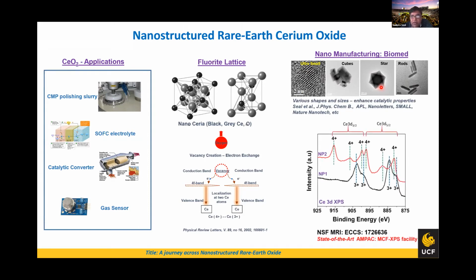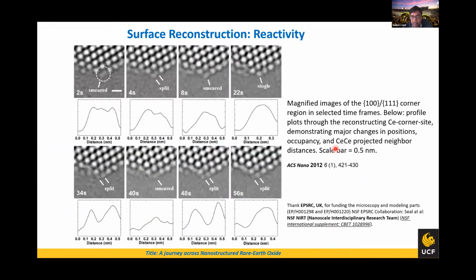The other thing is that we do a lot of work on surface chemistry. We are the only group that can make this material in a solution without precipitating out, and we can give you almost 60% of the plus 3, but also we can change the microenvironment of the material to get you more plus 4 at a fixed size as well. So we can play with the vacancies and the multivalencies of this material.